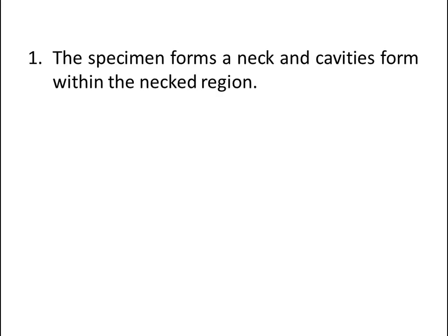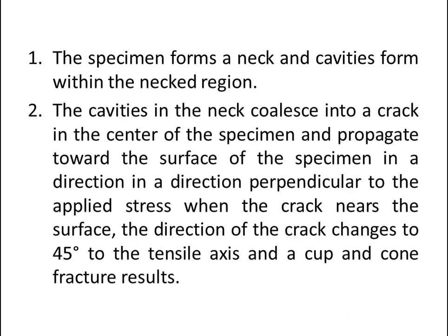First, the specimen forms a neck and cavities form within the neck region. Second, the cavities in the neck coalesce into a crack at the center of the specimen and propagate toward the surface in a direction perpendicular to the applied stress. When the crack nears the surface, the direction of the crack changes 45 degrees to the tensile axis and a cup-and-cone fracture results.